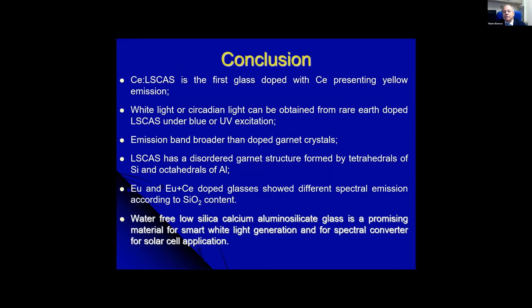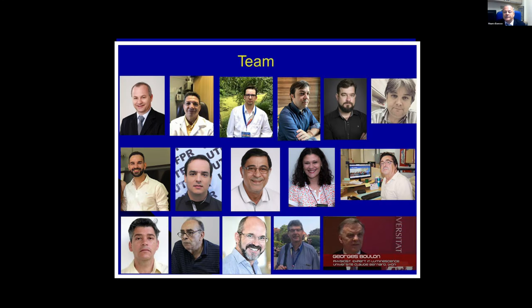So I'm going to conclude. The low silica glass was efficient to get yellow emission, different from other glasses we know. The circadian rhythm was simulated, and we were able to simulate emission similar to the eye response of the human being. The emissions are broader than crystals for all the dopings we used. It has a disordered structure. When we use the europium system, we evaluate the silica content influence on the emission. And so this glass, we think, is a candidate for smart white lighting and spectral conversion.